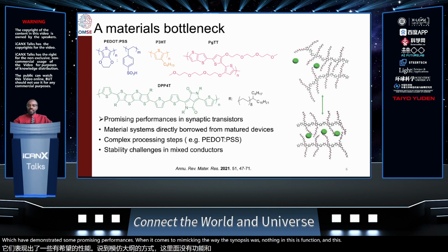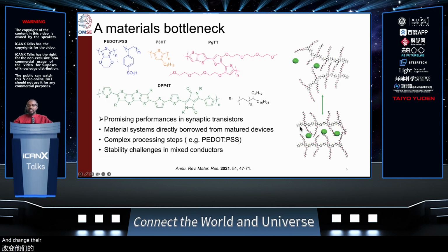And this is due to the ability to actually uptake ionic species and change their conductivity. And this uptaking and release of ions is attractive in such materials. However, even though these materials are showing great promise in terms of device demonstration, we still have several challenges. For example, the famous PEDOT:PSS is actually very difficult to process for most people, and we're still facing several stability challenges, making some of these candidates not feasible or not usable for real applications.